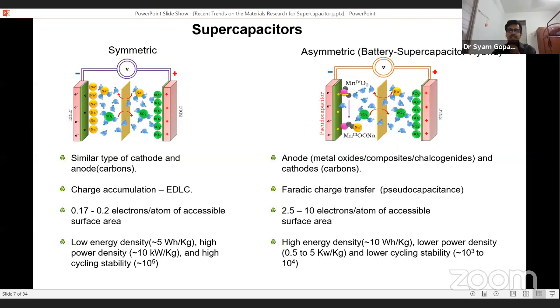Compared to that, an asymmetric supercapacitor has different anode and cathode materials, as well as a Faradaic charge transfer process, and the number of electrons involved per accessible surface area will be higher, as well as the energy density, but the power density will be lower. The important problem regarding the asymmetric battery hybrid is its lower cycling stability compared to the symmetric capacitor. Almost 100 times lower cycling stability compared to the symmetric one.